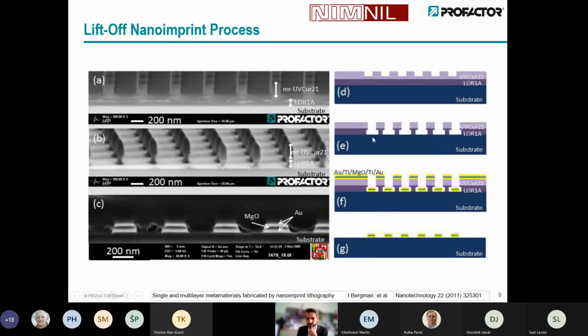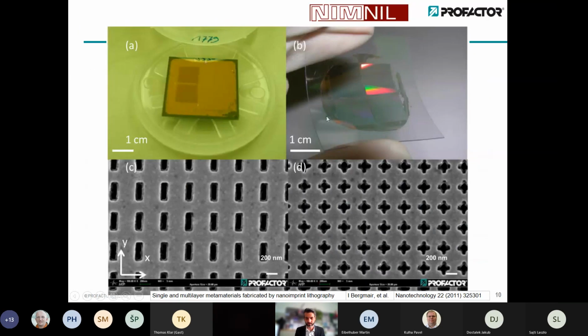And after this, the substrate here is free so that we can deposit actually different types of material. And in this case, we deposit a multi-layer stack of gold, titanium, magnesium oxide, titanium and gold. And after that, the resin, the imprinted structures here are removed using liftoff. And what remains are those structures directly on the substrate. If you have such a substrate, it looks like this. So it was a few square centimeters only in this case.